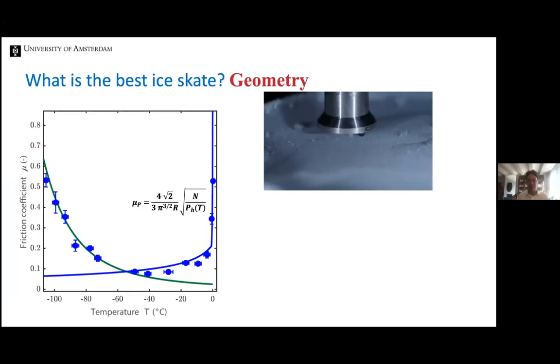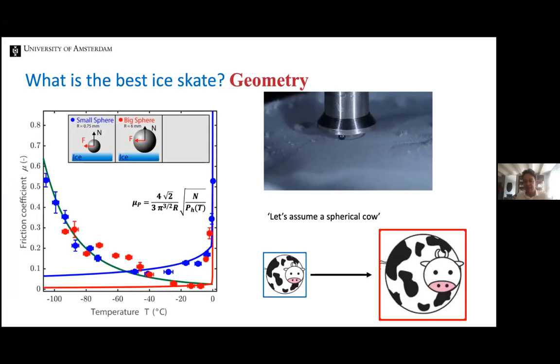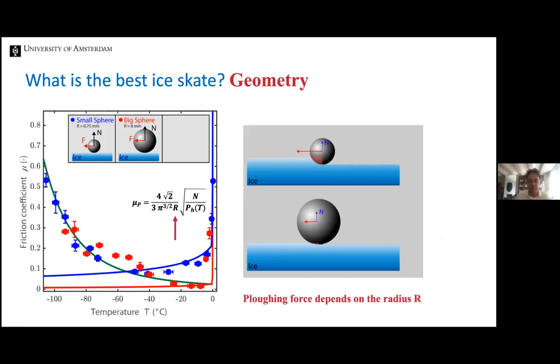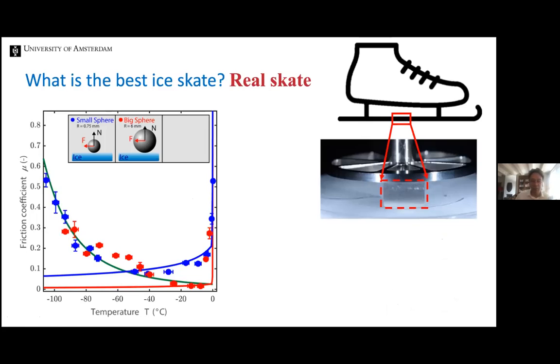So let's ask the question what the best ice skate is. Part of it is, of course, the geometry, and we had this curve for our little steel ball. Now, let's approximate the skate as a spherical cow, if you like. If you take a much larger sphere, you immediately see that the result becomes very different, because the sphere is larger, the normal force gets distributed over a larger area. And so the increase due to plowing friction happens at a much later time, at a much higher temperature. And so the ideal skate, this is what I just said, is of course the real skate,